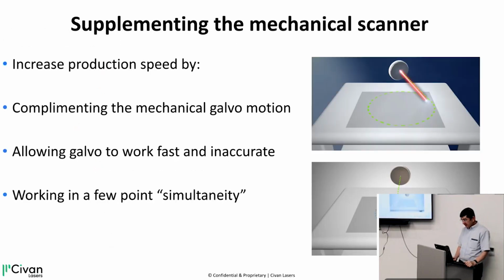And in terms of complementing the galvo scanner, the bottom line is that you can go fast but inaccurately with the galvo scanner, and electro-optically jump to many points simultaneously, like in 1 millisecond. Instead of sintering 1 point, you can sinter 10 points. You can go very inaccurately and fast with the galvo scanner and still be very accurate electro-optically.